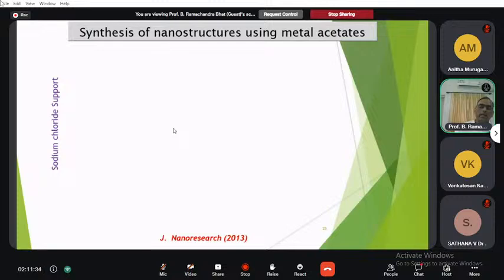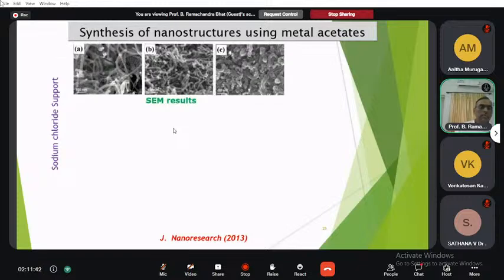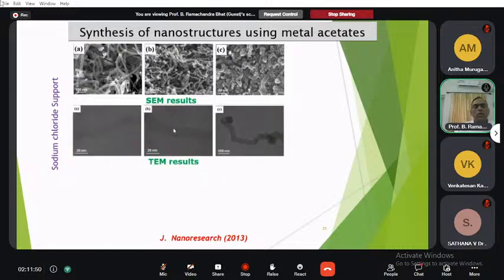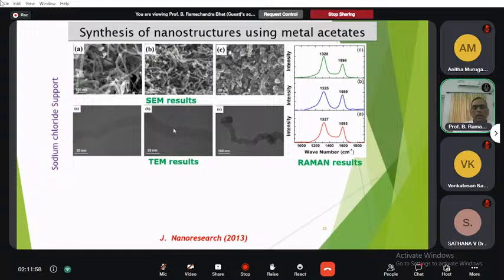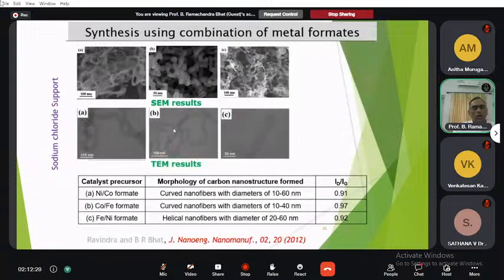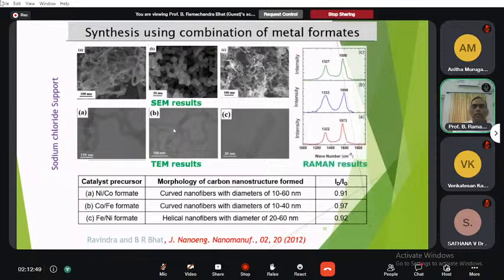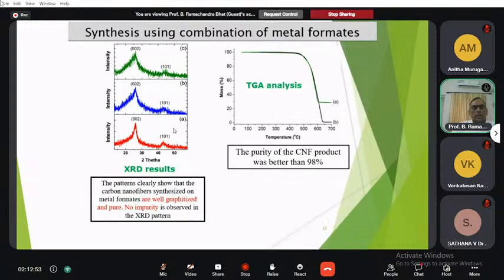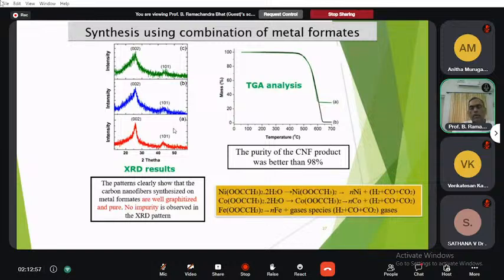The metal formates or metal acetates are taken, and we have changed the support from calcium carbonate to sodium chloride. So these are some images of the material we have synthesized. It is carbon nanofibers, and the TEM image clearly shows that there is no hollow core in the material. That shows that it is a CNF. And this is a Raman with the nickel cobalt formate, cobalt and iron formate, and iron and nickel formate, where the ID by IG ratio is just below 1. You can see that the materials are well prepared here, and the CNFs are formed, and the combination gives a very good result here. The purity is also more than 98%.